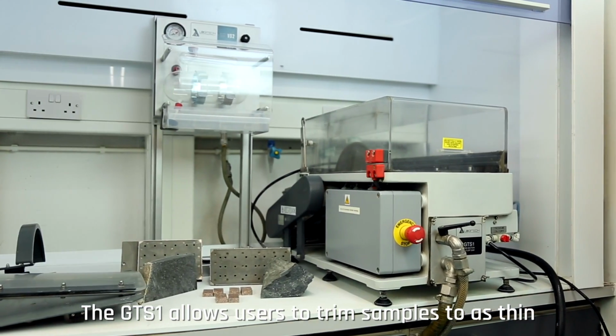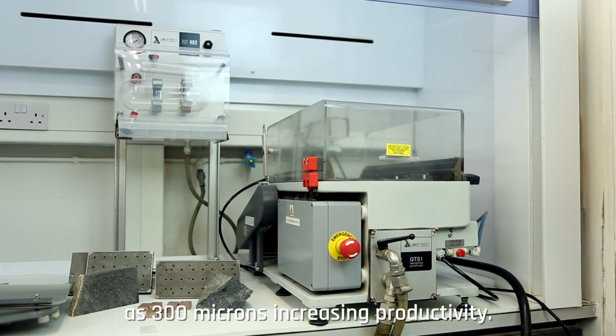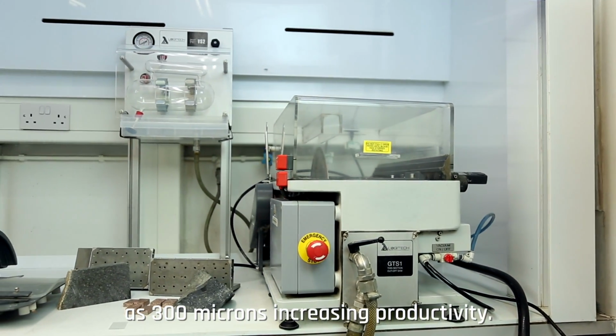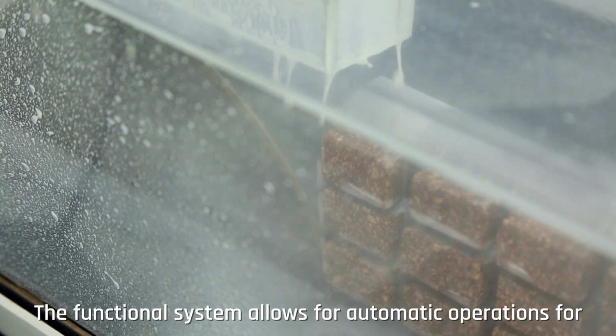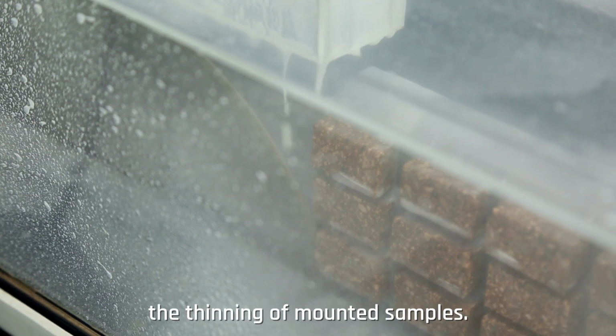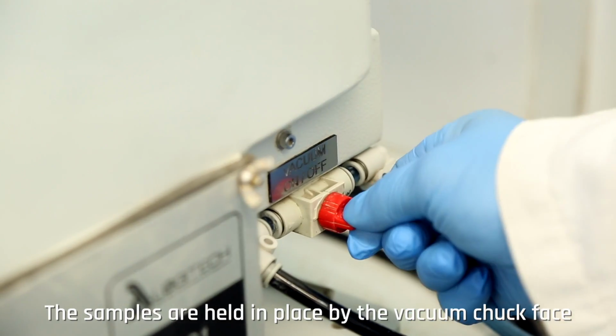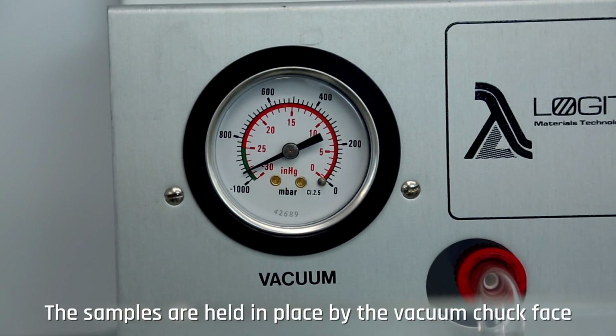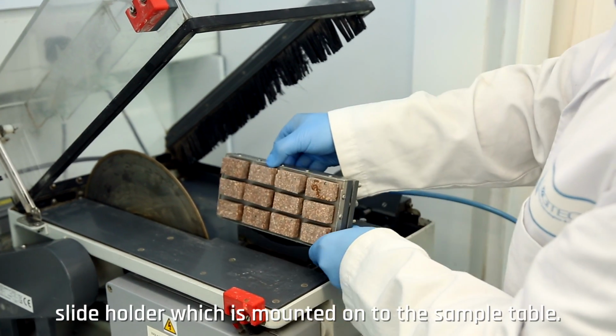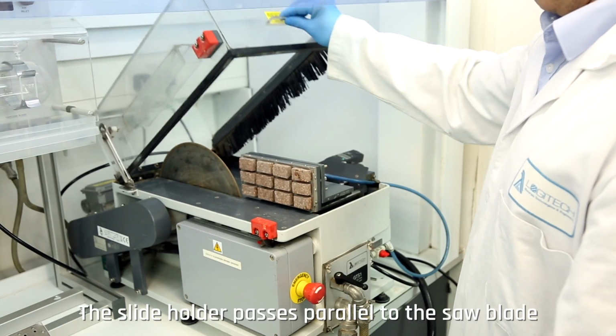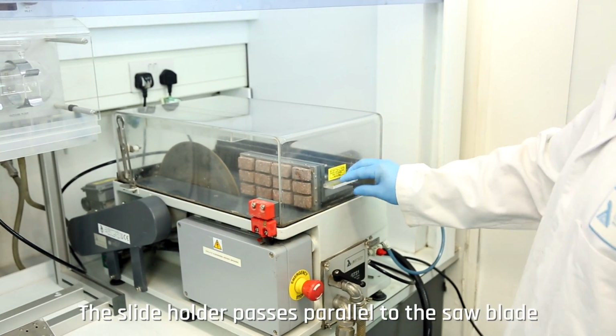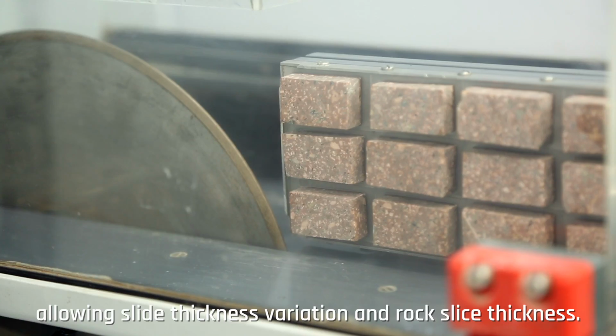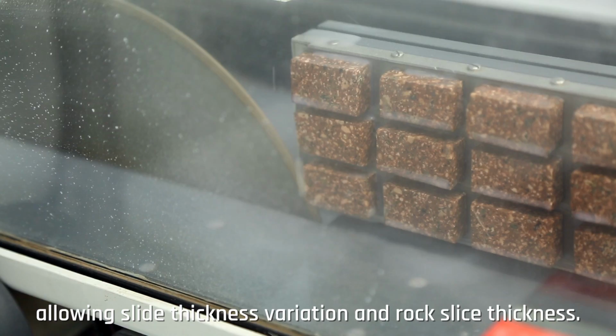The GTS1 allows users to trim samples to as thin as 300 microns, increasing productivity. The functional system allows for automatic operations for the thinning of mounted samples. The samples are held in place by the vacuum chuck face slide holder, which is mounted onto the sample table. The slide holder passes parallel to the saw blade at a user-adjustable distance, allowing slide thickness variation and rock slice thickness.